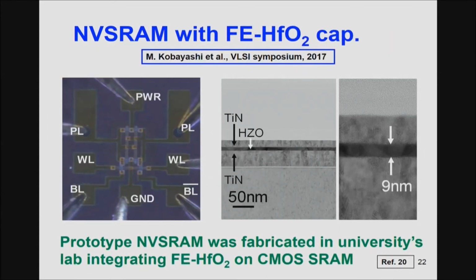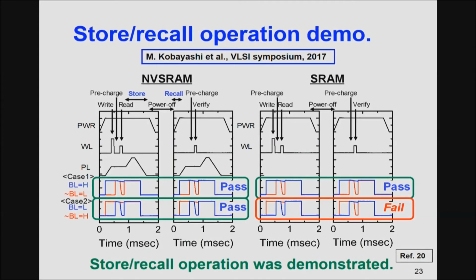So students and I started investigating this structure, and we fabricated a prototype of the NVSRAM with a ferroelectric hafnium oxide capacitor like this. This is a microscope image and these are the capacitors. Here's the cross-section TEM of the ferroelectric capacitor. It's 9 nanometers thick and uniformly crystallized. We tested the functionality of this NVSRAM, as well as an SRAM fabricated on the same chip.